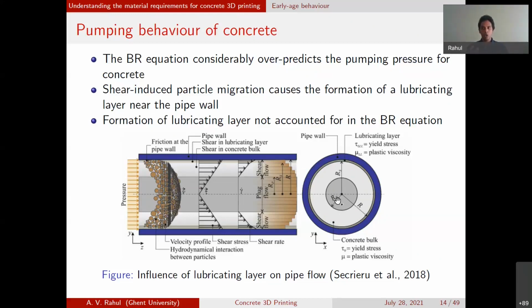So instead of analyzing it as a homogeneous fluid, we need to analyze it as a heterogeneous fluid. A heterogeneous fluid, in fact, consisting of two Bingham fluids: a Bingham fluid of the bulk concrete and a Bingham fluid of the lubricating layer. This heterogeneous fluid has to be analyzed to make a realistic assessment of pumping pressure. Once the lubricating layer effect is taken into account, a sufficiently fair estimate of the pumping pressure can be made. I'm not going into the mathematical detail of how this can be done, but this is important, and it can create a significant error in your calculation if it is not taken into account.